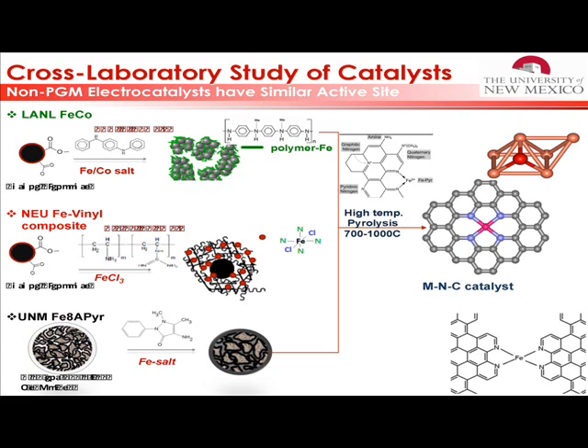So this essentially is a DFT model of the nitrogen spectra's fine structure. And with that, we do a cross-referencing with different methods of different activities. And we have in our possession catalysts from Los Alamos, from Northeastern, and from our group to compare, because we work in one big program. And with that, we can actually say that all these catalysts have an active site that is very similar to each other, although they're made in an entirely different way from different precursors.